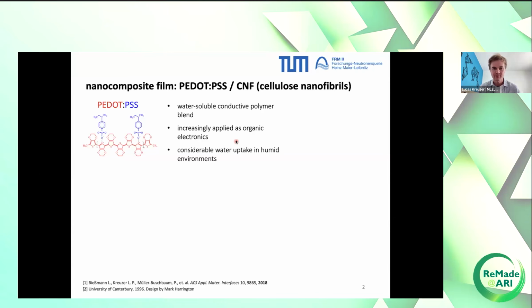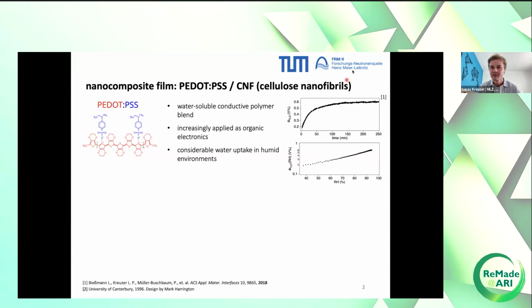This is all great, but it also comes with one drawback. If you expose it to a humid environment, it takes up a significant amount of water, as you can see here on the right. This is the water content inside the films as a function of time and relative humidity. These films absorb water quite quickly, in a matter of minutes. Already at intermediate humidity levels, 40 to 50%, we have 20 to 25 volume percent of water inside these films, and it gets increasingly worse at high humidity. Water inside these films leads to a swelling mechanism, structural rearrangements, aging and degradation mechanisms, so long-term stability is not very good, and eventually you have a loss in performance. Here the performance is the electrical conductivity. So these films degrade after some time, and this is, of course, something we don't want.